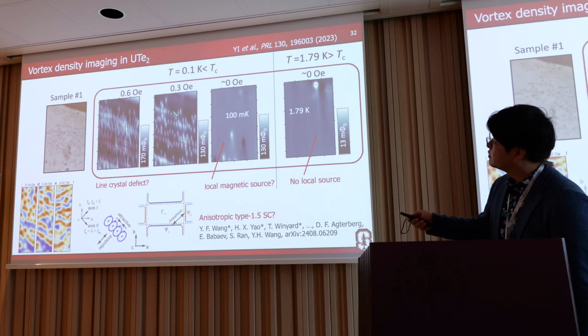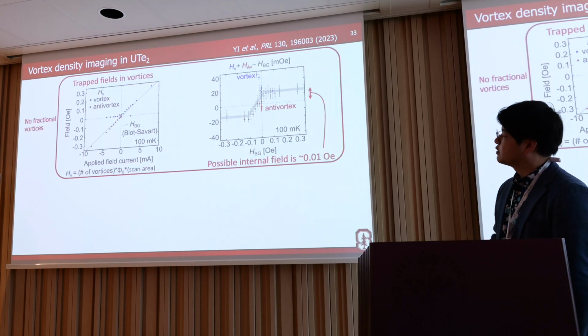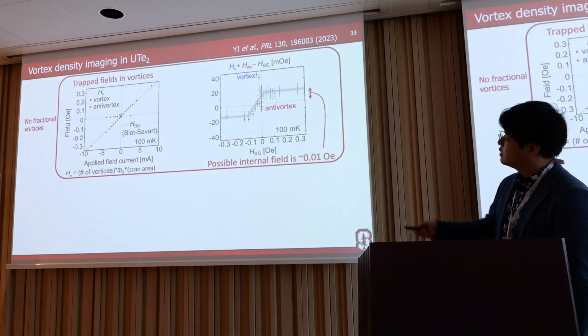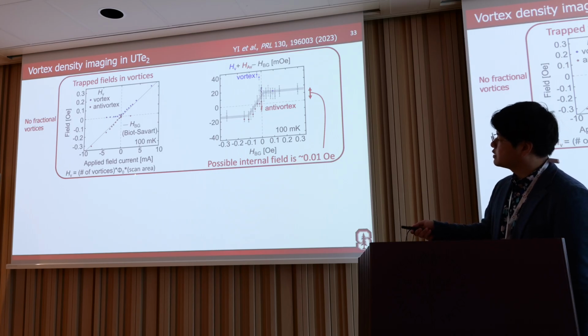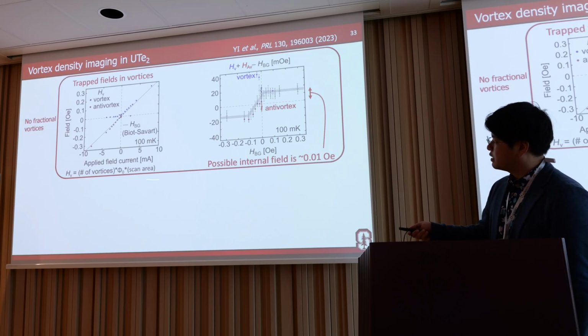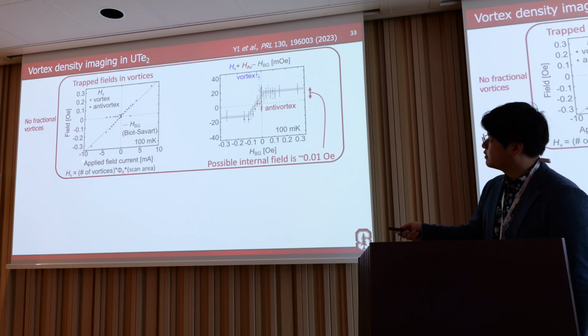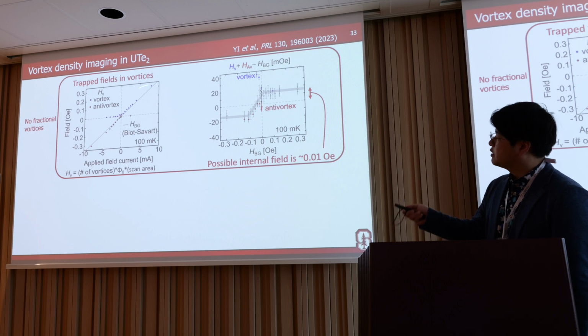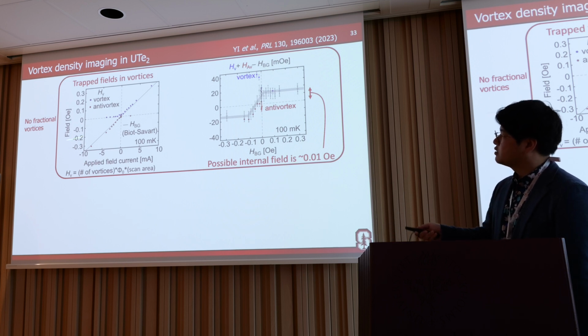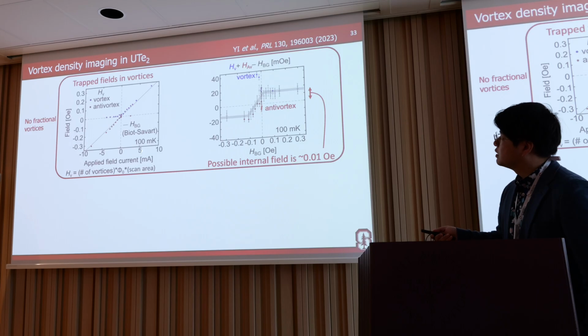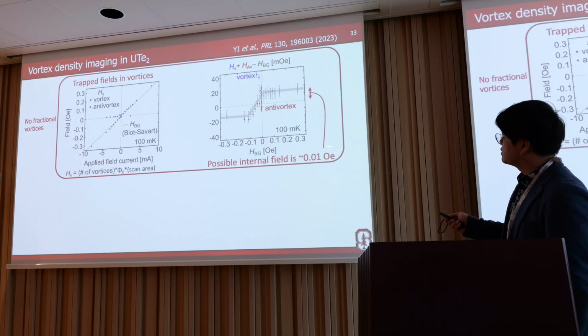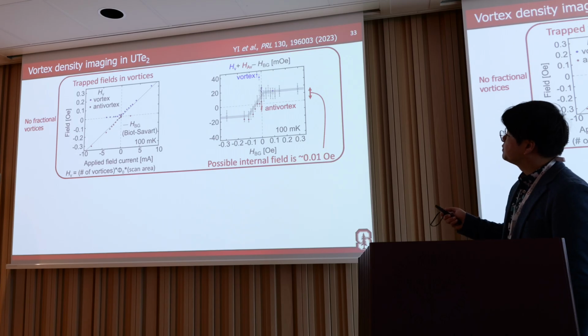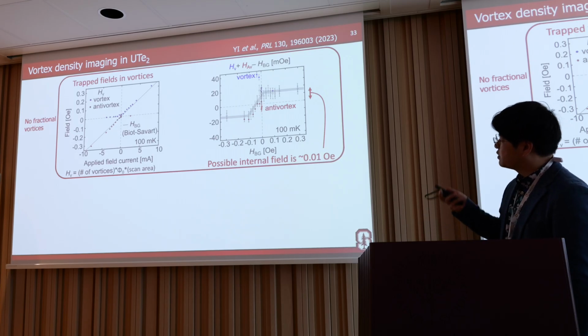And each vortex looks very quantized. It's not fractional. Here I plot the magnetic flux trapped in the vortices, the number of vortices multiplied by the scan area, plotted against the applied field current. It increases linearly, and there's no evidence for fractional vortices. But there's a small gap there. It's 0.01, which is very small. We suggest there's some possible internal field.